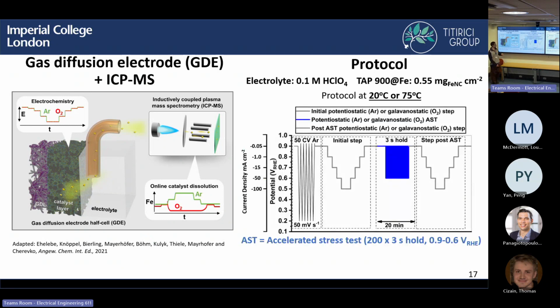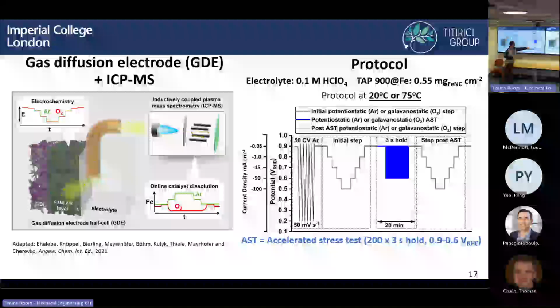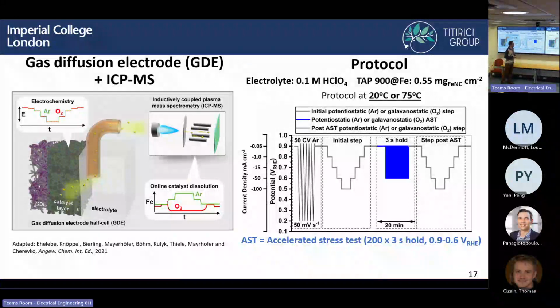And to summarize the protocol, we saw from the flow cell that we need to do at least 50 CVs to really stabilize the measurement. So we do that first, and then we step the potential and the current down from 0.9 to 0.5 volts in this initial part. And then we do a short accelerated stress test, again going from 0.9 to 0.6, holding at that potential for 3 seconds. And then afterwards doing the same measurement.